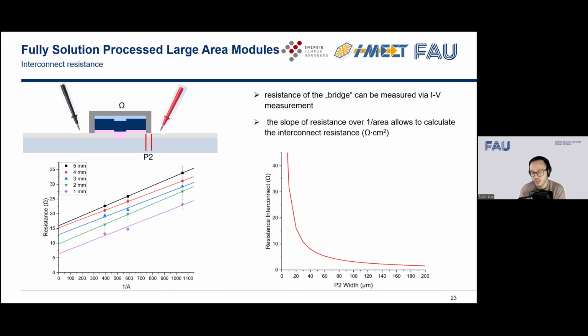And with that, you can do a simple calculation. So on the right-hand side, you can see a graph with the variation of the P2 width. If you start with very thin P2s, you end up with quite high resistances, and it gets significantly lower within the region of 20 to 80 micrometers. So here you can really win in effective series resistance within the interconnect, which explains why you can get higher fill factors.